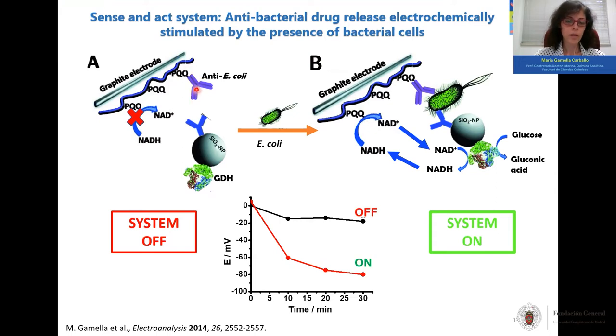And also we immobilized in this layer an antibody against E. coli. Additionally, we prepared these conjugates through the immobilization of the same anti-E. coli antibody and this protein that is an enzyme called glucose dehydrogenase that, as you can see on the left part of the slide, reacts with glucose in the presence of NAD+. What happens if we don't have E. coli in the solution? Well, we are not going to have GDH bound to the surface of the electrode, therefore there's no NADH production on the surface and there's no oxidation and no electron movement. Therefore, when we measure the potential within time, we could see no shift in the potential regarding the zero time, and our system is off.